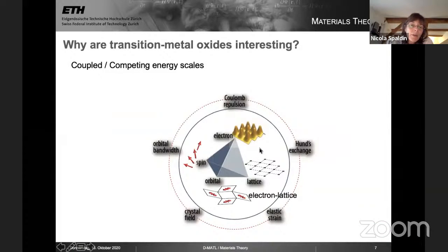So let me just summarize. Another way to think about that is that the relevant energy scales in transition metal oxides are all very similar to each other. And this leads to either coupling or competition between them. So for example, the Coulomb repulsion that comes from the electron-electron correlations is usually of the order of tenths to an electron volt. The widths of the bands, which come from the bonding between the oxygen and the transition metal, are similar to the Coulomb repulsion.